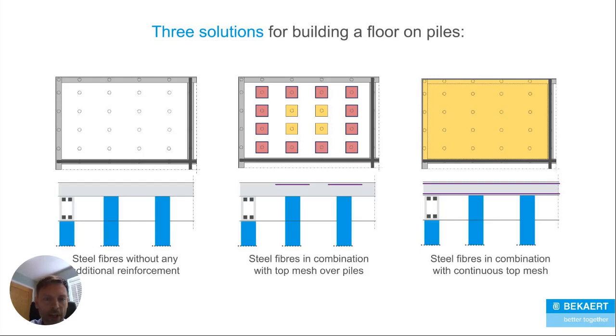But this evolved thanks to our friends in Holland who developed a structural code specifically for floors suspended on piles and reinforced with steel fibres. And what they decided was that traditional steel was placed where it was actually most needed. They analysed that sagging moments between piles were very rarely the failure mode, and actually hogging moments over the piles or punching shear was the theoretical failure mode of these floors. So you can see fibre reinforced concrete, but with a lot less mesh.